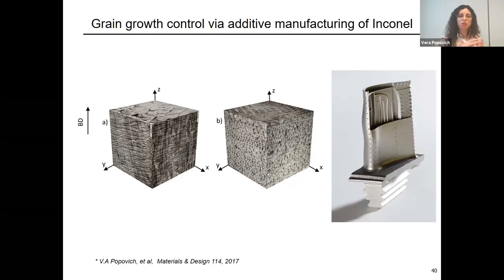But my message here is that what we developed also in our group is tailoring the process parameters. So tailoring how much energy you apply into the layer, yeah? What is the layer thickness? Do you apply the preheat on the base plate on which you grow this all? You can grow different types of grains in the material. And you can do this locally anywhere in the components, by changing the laser parameters, let's say.